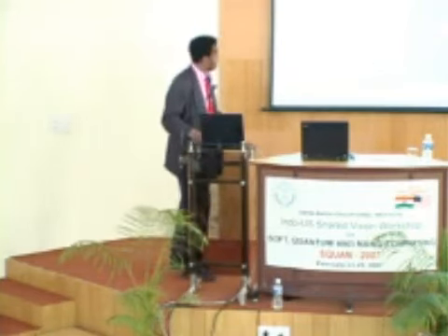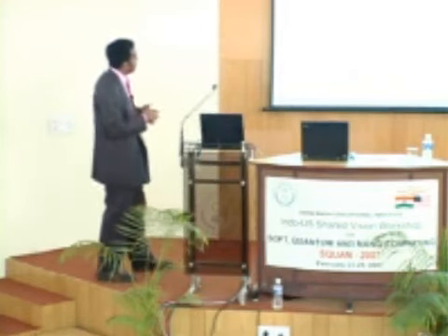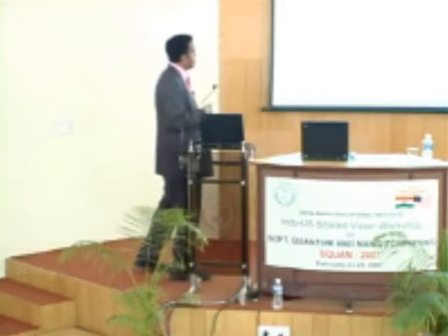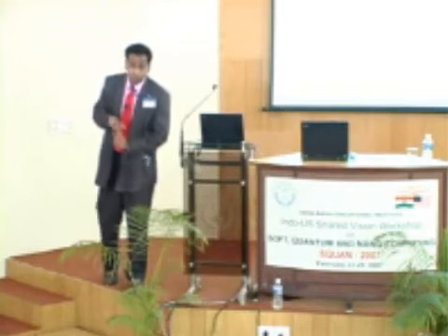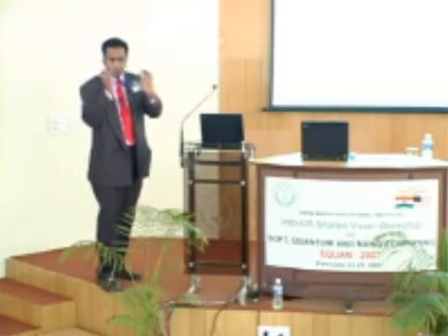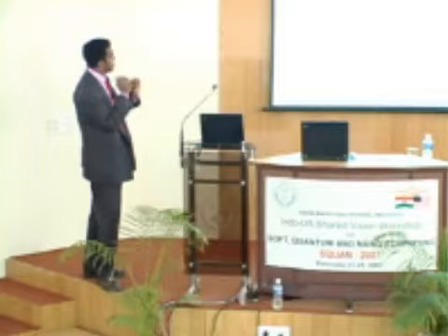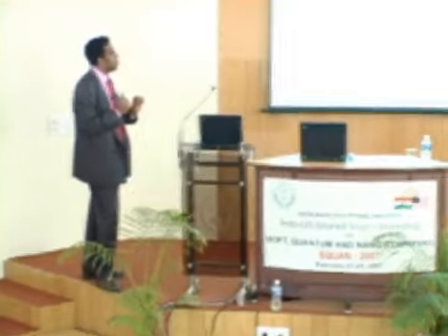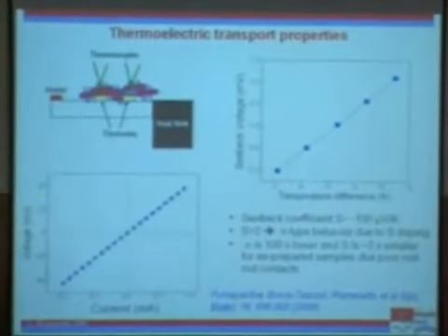physical templates really. And the idea here is, of course, since it's thermoelectrics, you want to get high electrical conductivity and you want to get low thermal conductivity, right? The electrical conductivity you want to tune by using quantum confinement, so getting more states near the Fermi level. But low thermal conductivity you want to obtain by size confinement, because of the phonon scattering from the surfaces and the boundaries of the structure itself.